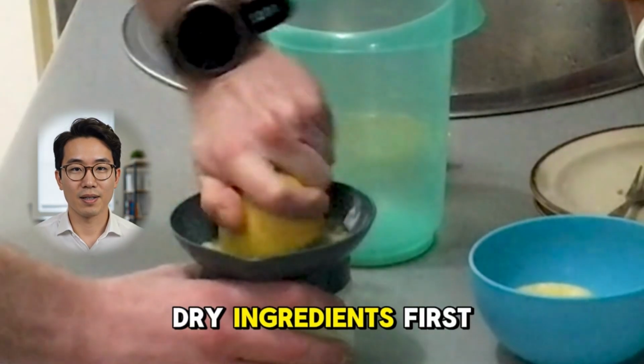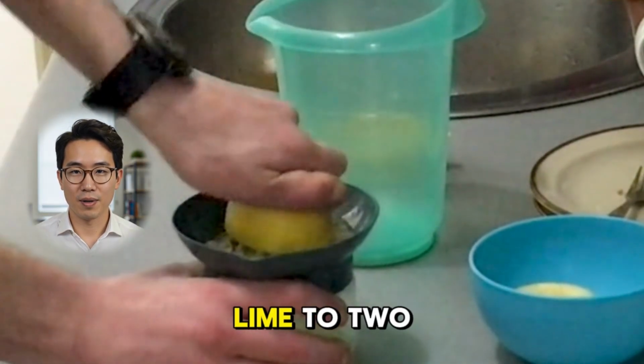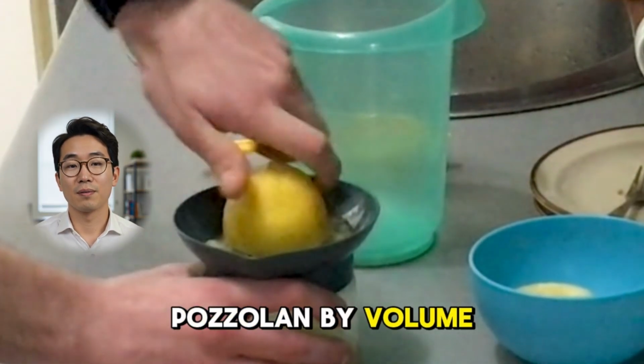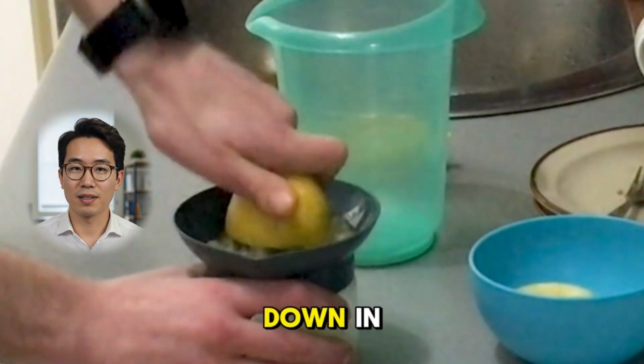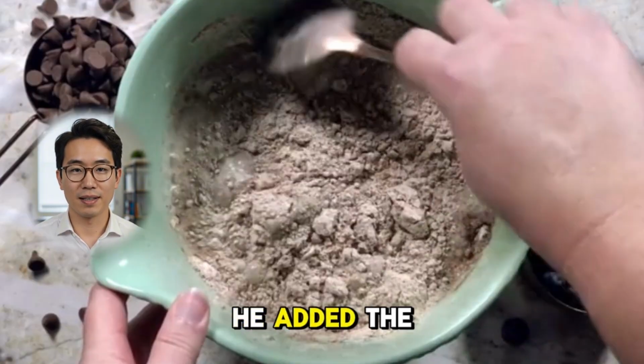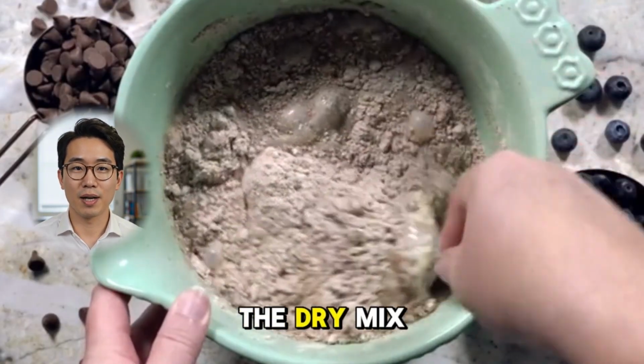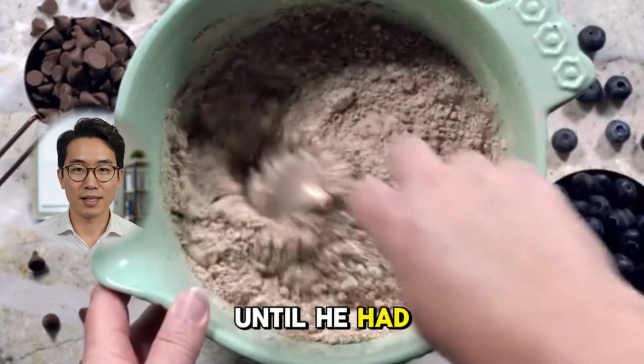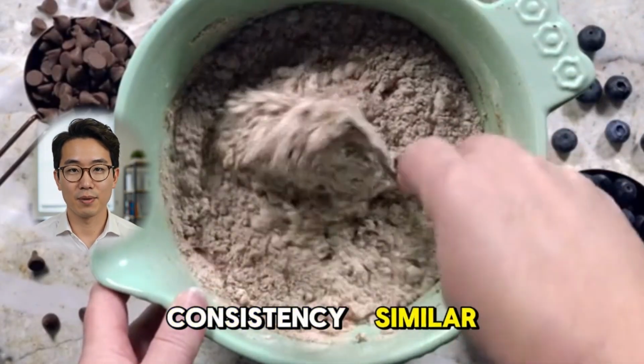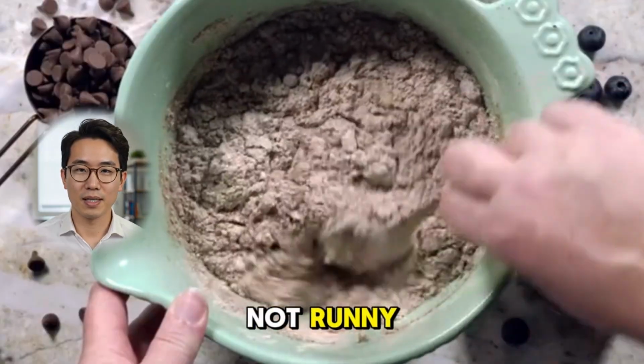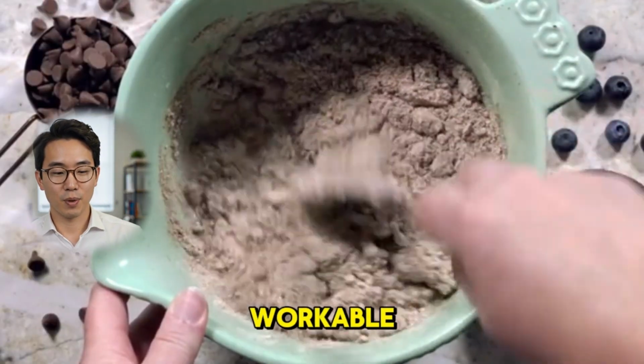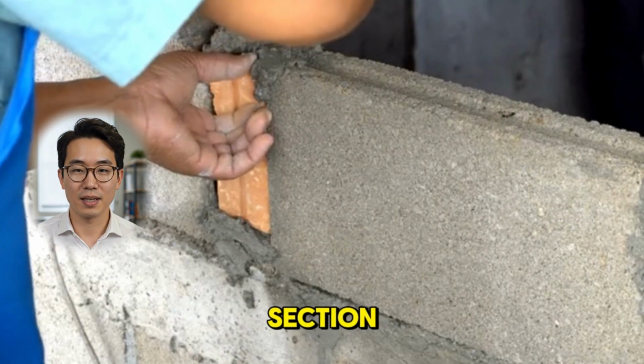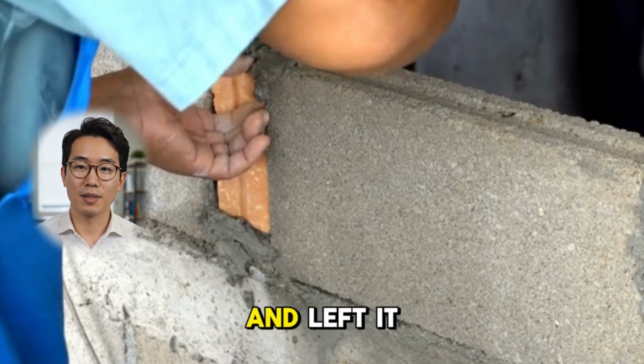He mixed the dry ingredients first, 1 part hydrated lime to 2 parts pozzolan by volume. The exact ratio Vitruvius had written down in 25 BC. He added the seawater gradually, working it into the dry mix with a standard mixing paddle until he had a thick mortar consistency. Similar to peanut butter, he described it later. Not runny, not crumbling, just dense and workable. He packed it into the damaged section, shaped it against the existing wall, and left it.